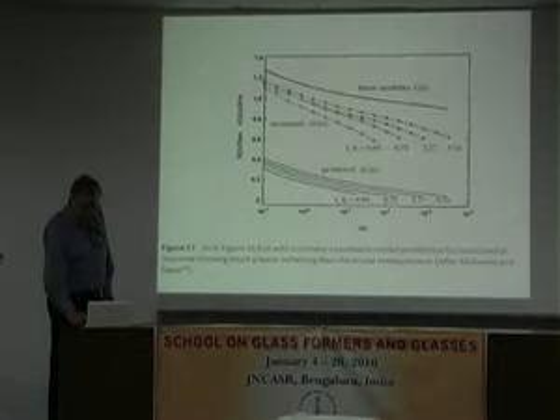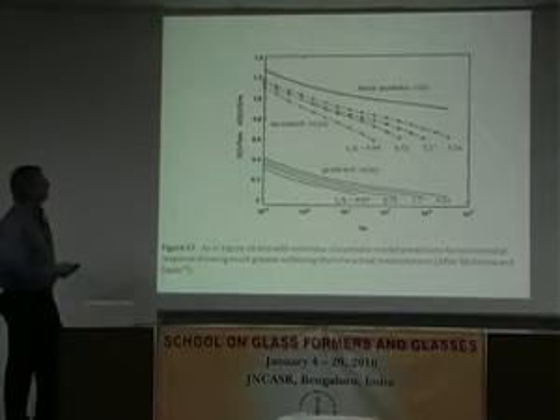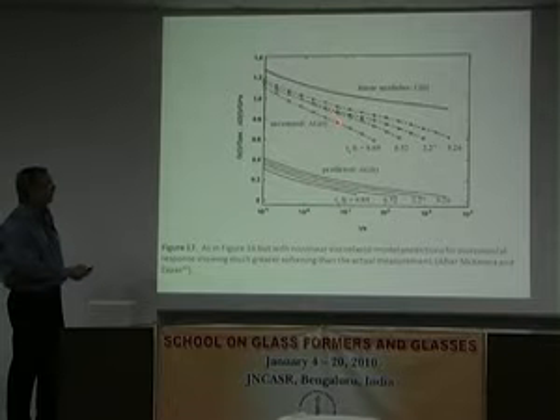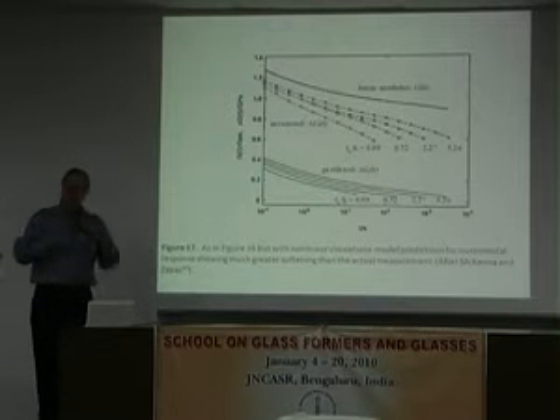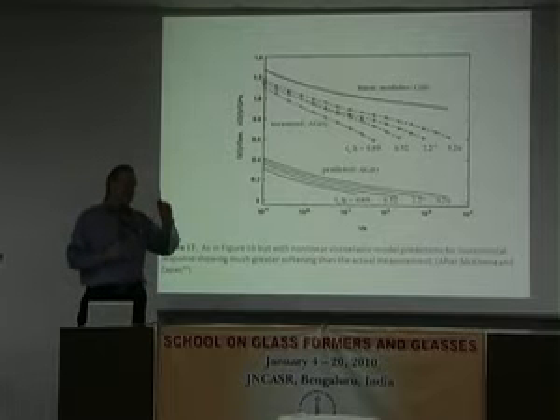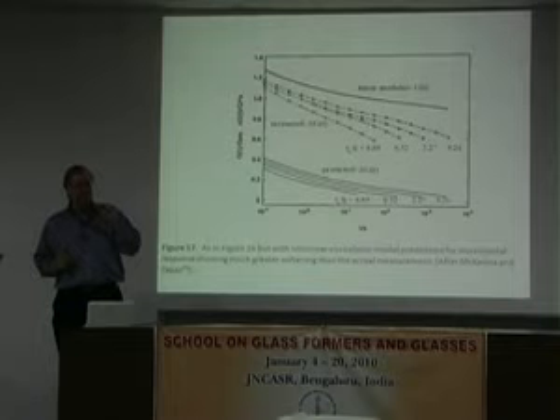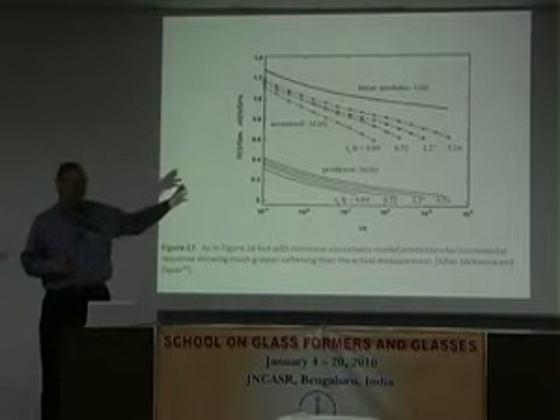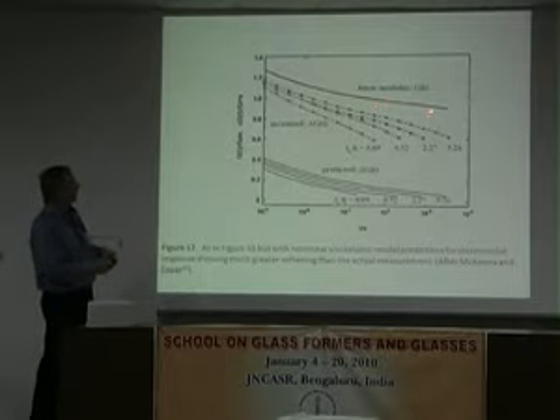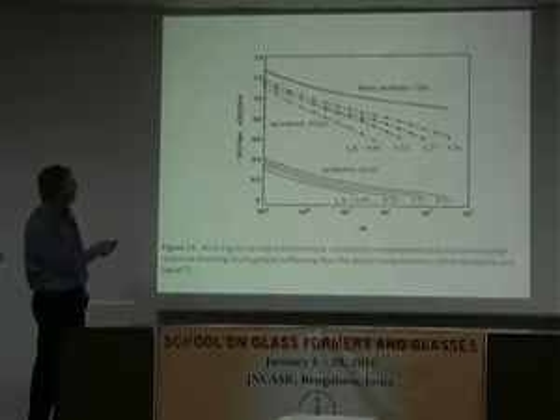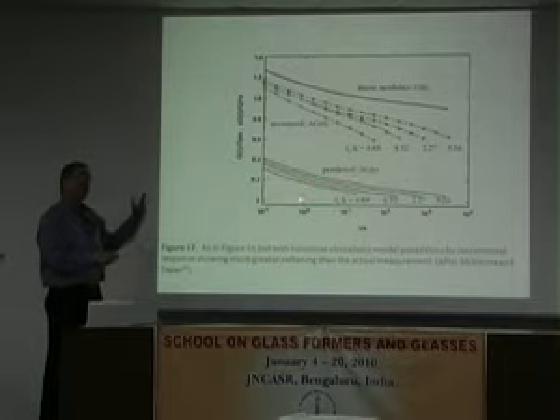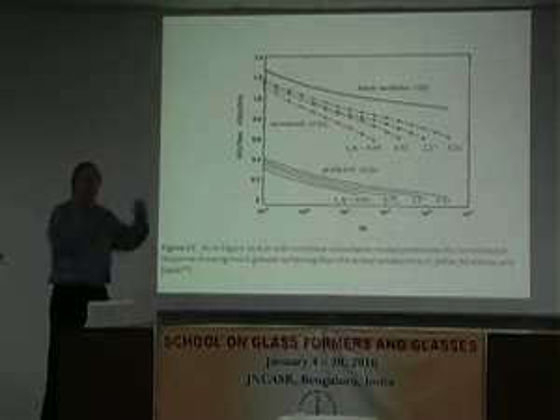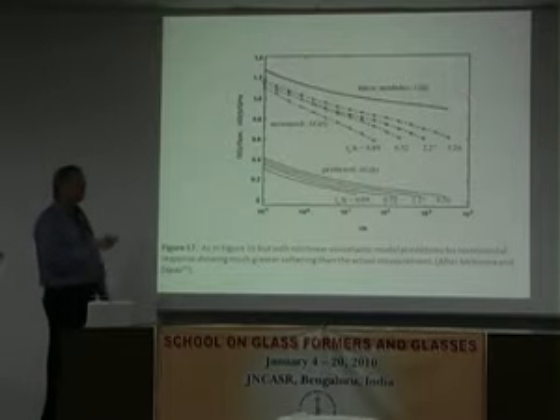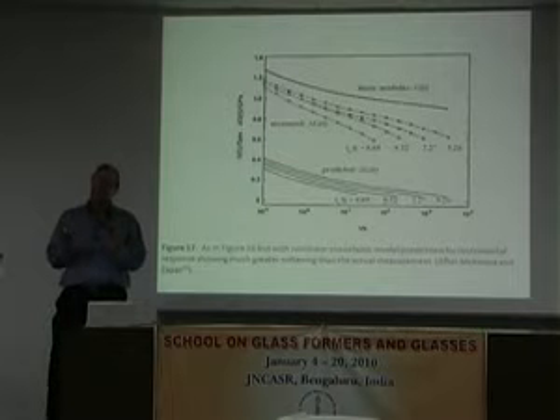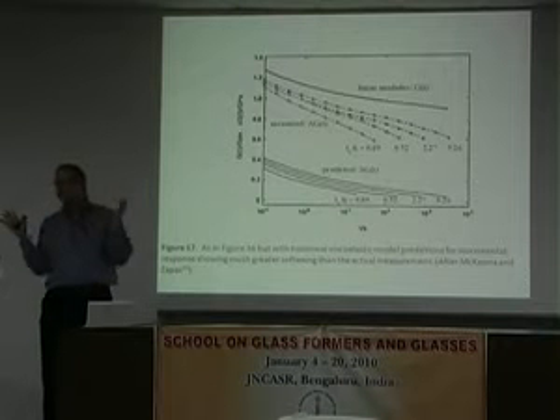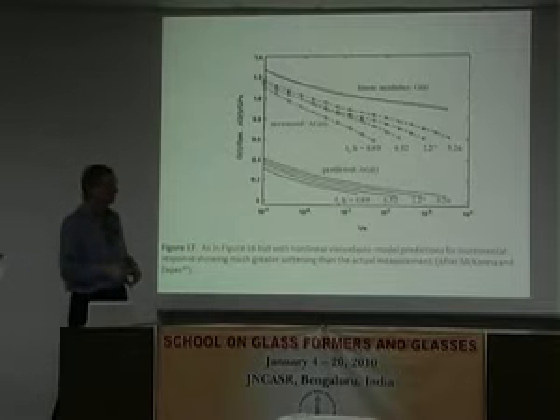And so we did some calculations, and actually we got very surprised. The first thing is that we didn't predict this at all. We actually underpredicted it. So in fact, the reason we say it's a complicated problem is that without knowing the nonlinear constitutive law that describes your material, you can't interpret this experiment. Because if I interpreted it relative to the linear constitutive law, I would say I rejuvenated it. If I interpret it relative to this nonlinear constitutive law, I actually accelerated aging, made it stronger, and so on. So we simply said that when you do too complicated an experiment without having the right set of rules, you really can't interpret it. That's really the bottom line on that.